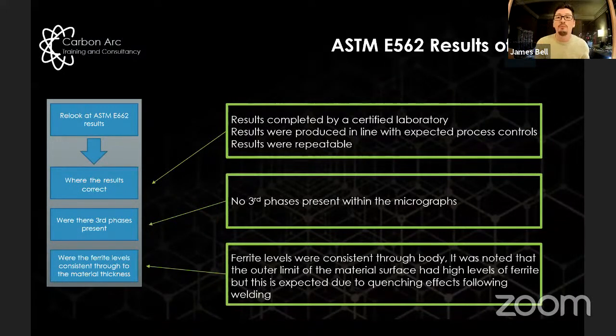So the first thing we did was go back to our qualifications and review our ASTM E562 data, which is the point count of the ferrite, which is a reading which we believe should be absolutely correct, because we've cut the sample open and we've looked at it and we say, this welding process on these welding variables produces this value. It's not an NDT test, it's a real countable value. And in all, we weren't seeing an issue. We recounted some parts and we're like, no, these qualifications are correct. We're welding, we should be getting a good value. The ferrite balance was correct. We've got no third phases and no secondary austenite, no sigma, nothing like that. It was all clean. So we moved on to the next thing to look at.